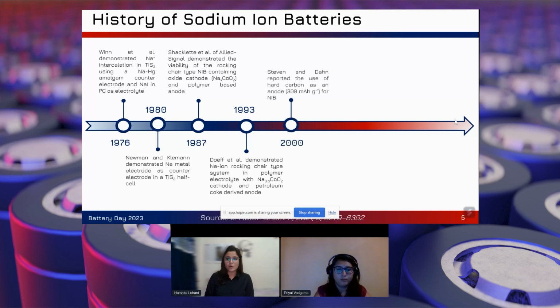Now, in 2000, finally, Steven and Dahn were able to find an anode, which is also considered the state-of-the-art anode for sodium-ion batteries today, which is a disordered type of carbon known as hard carbon, and which gives a capacity of 300 milliampere hour per gram, which is very close to the capacity which graphite gives for lithium-ion batteries, which is 372 milliampere hour per gram, theoretically.